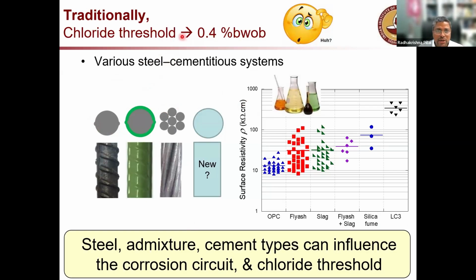Now conventionally or traditionally, we have used 0.4% by weight of binder as a critical chloride threshold, which is the amount of chloride required to initiate corrosion. Now, this number might change as you change the type of concrete which you use and as you change the type of steel which you use. Okay. Now, I'll talk to you about that a bit later.